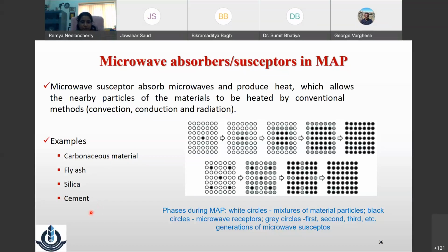So that means, say, I have one microwave absorber that is added to my feedstock. Suppose my feedstock is a non-microwave absorbing material, and here I have one microwave absorber. So now this absorber will absorb microwave, and later on it will be conduction heating, right? So this will be conduction heating. With the conduction heating, the temperature of the surrounding is improved. It will further conduct the heat to the outer surface, and so on. Now this heating rate can be further improved if you add a little more of the microwave absorber. That means you can tune the ratio of microwave absorber to your feedstock to enhance the heating rate. Right? So here you can see the increase in temperature, the heating rate, time, all these can be tuned based on the ratio of the absorber used.